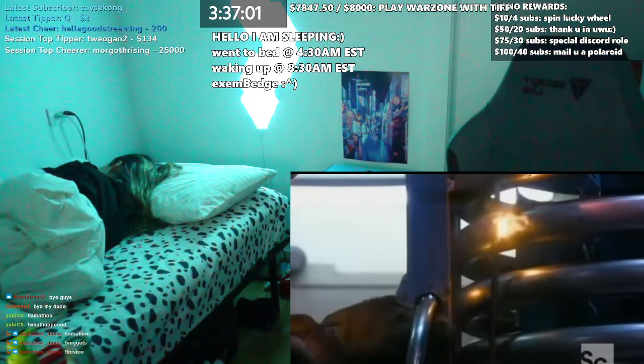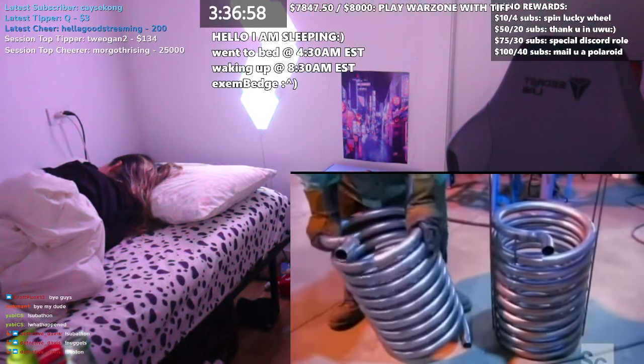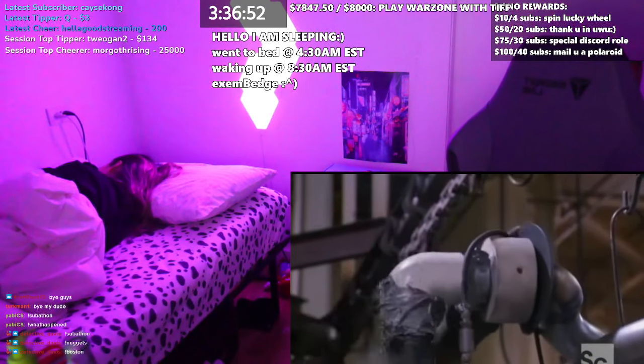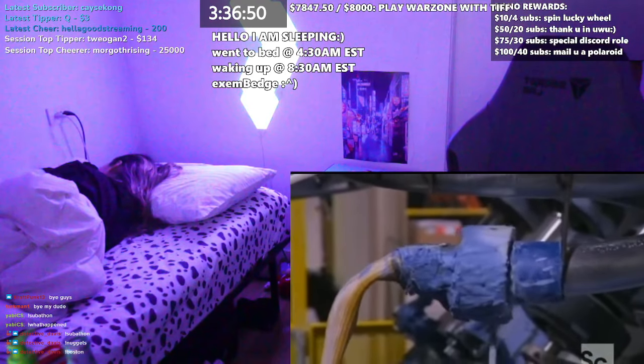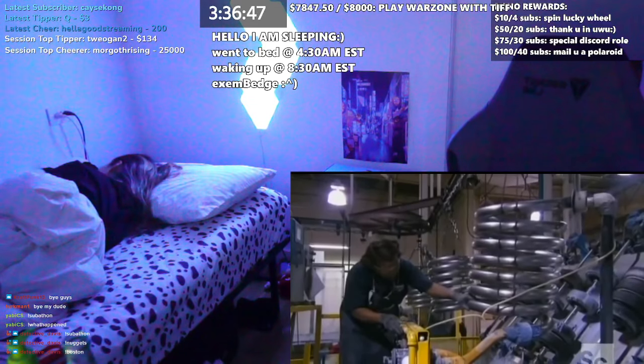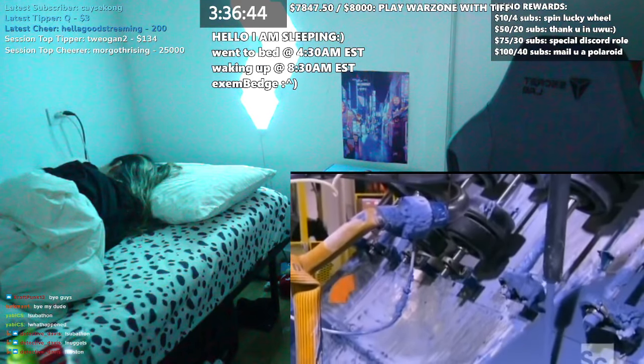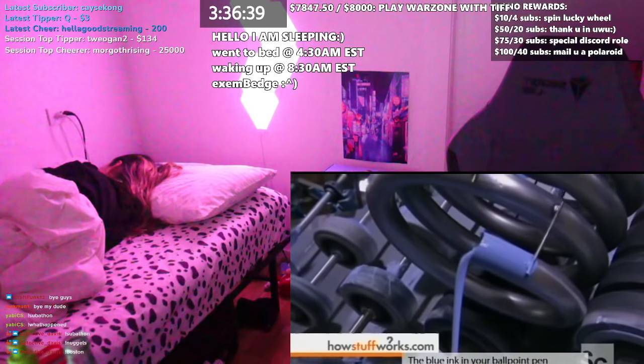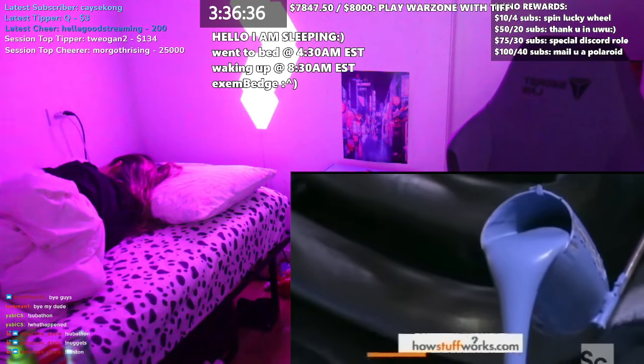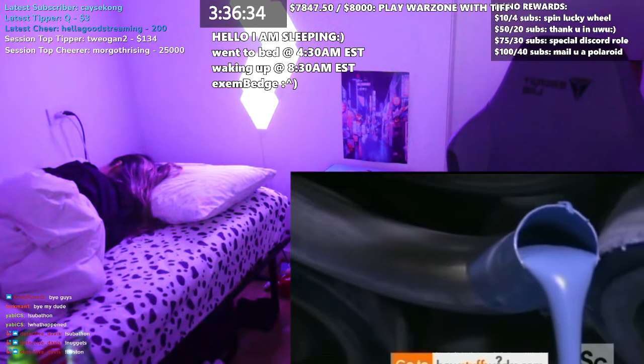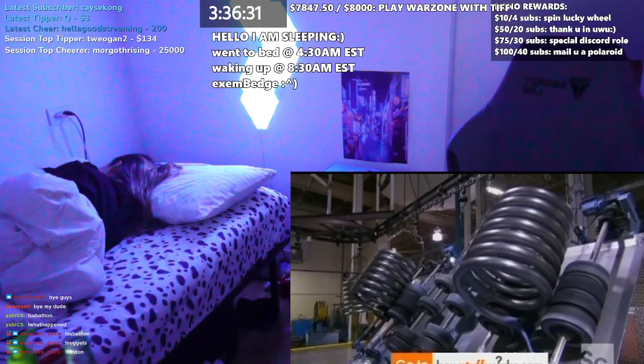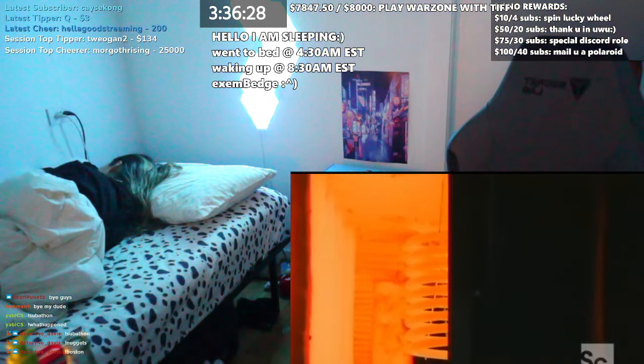A welder fuses steel rods to the sides of the coil, making the flexible heat exchanger suitably rigid. Next, a machine pumps a ceramic enamel through the pipe from the bottom up to ensure full coverage. This coating protects the interior of the pipe against corrosion. It takes about 6 minutes to fully coat the inside of the pipe and drain the remaining liquid. It takes about 15 minutes inside a furnace for the coating to cure and become rock hard.